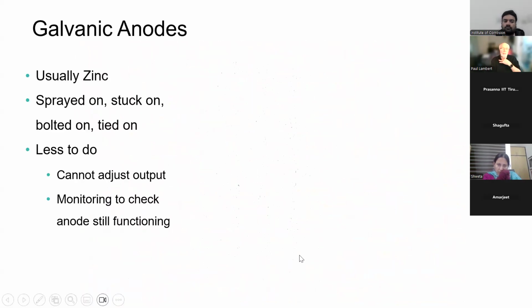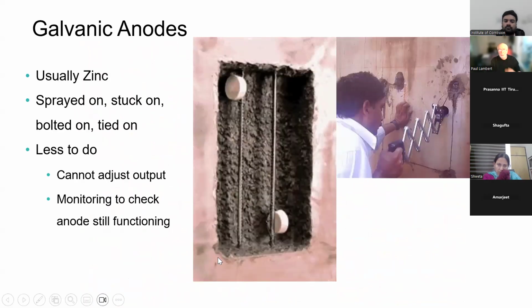Just quickly going retro, galvanic anodes have become more widely available, generally based on zinc. Often like the two you can see on the left there, they're used for tying on at the edge of repairs, and they stop corrosion occurring in the area adjacent to the repair. Otherwise, that area has still got chlorides in and it will start to corrode. The zinc in there is in a special mortar that keeps it active, and it's very high alkalinity, stops the zinc from passivating, so it'll carry on corroding.